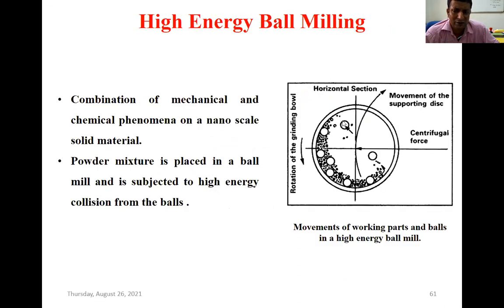Here we can see these balls are there, and small powders, our specimen powder. The whole rotation is taking place at very high speed, and via that, of course, collisions will be there. In between, particles are there, as we have seen in the different stages. So the particles will be broken, the particle size will reduce, and in turn they will react among themselves also at room temperature, and phase formation will take place.